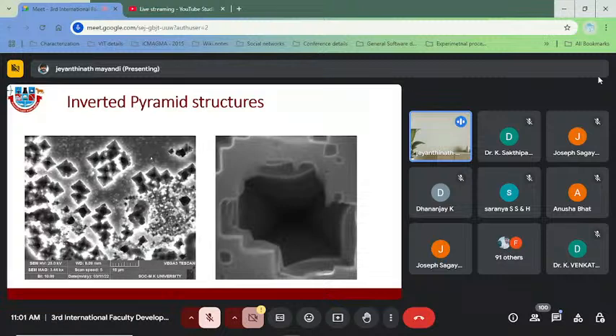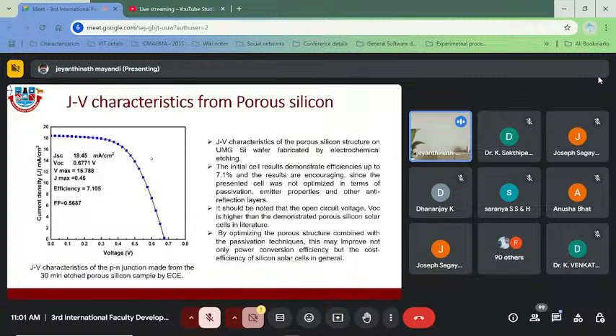So we were trying to make pyramid-like structures with nanostructured layers. And this would also give, in future work, a better performance of silicon solar cell devices with combinations of our porous silicon and hybrid nanostructures. We were able to make a device in our laboratory conditions, and you could see that our efficiency is almost around 7.1%.